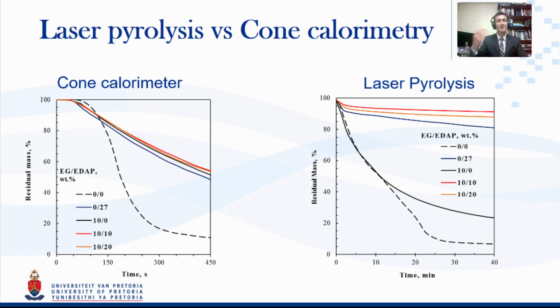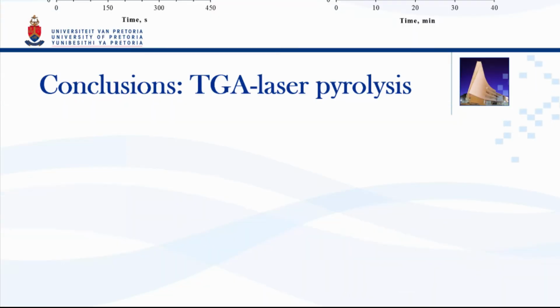The best result is still in the 1010 binary system, and the 1020 is second best. Once again, a really great result both in cone calorimetry and on the small scale, that our cheaper additive mixture was actually the better result.